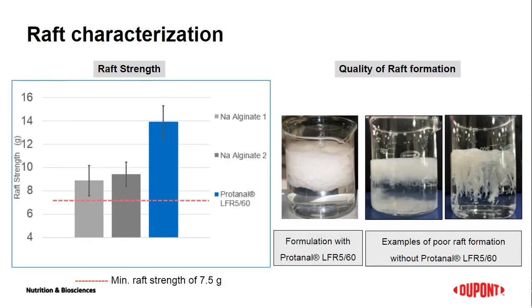So now moving on to the raft characterization. The suspension formulations which are prepared from different sources of sodium alginate are characterized for the raft strength using the texture analyzer. The bar graph on the left side of the chart shows the raft strength exhibited by the different formulations. The formulation prepared from Protanal LFR 5/60 has shown higher raft strength. The images on the right show the quality of raft formed from the different formulations. The images show that Protanal LFR 5/60 has formed a uniform raft which has excellent thickness compared to that of the other rafts formed.